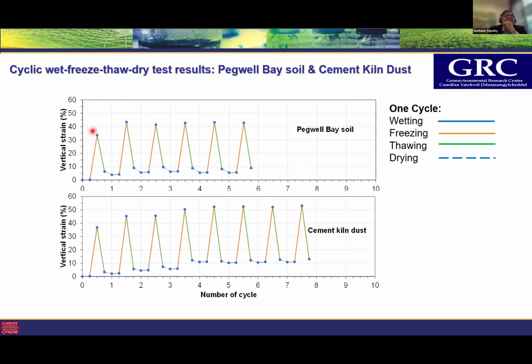This is the cyclic wet, freeze, thaw, dry test on Pegwell Bay soil and cement kiln dust. A similar upward movement pattern was also noted for both. However, the strain magnitudes were different for different materials, and unlike Speswhite kaolin, the swelling and shrinkage strains for these materials are very little, but both exhibited significant frost heave and thaw settlement.